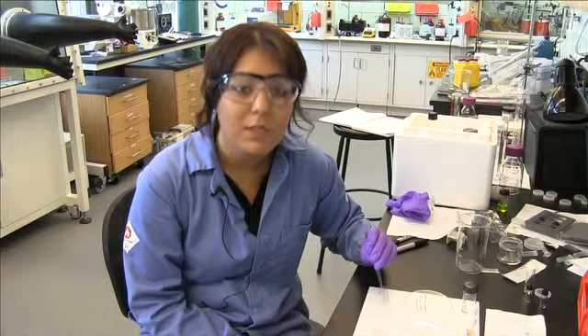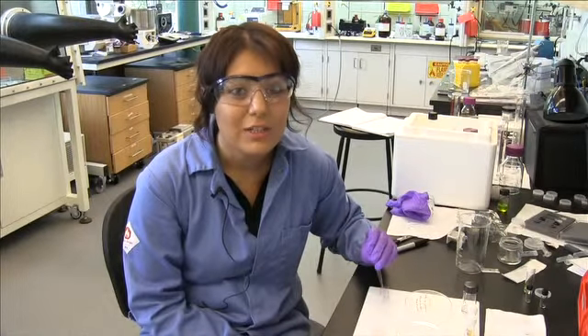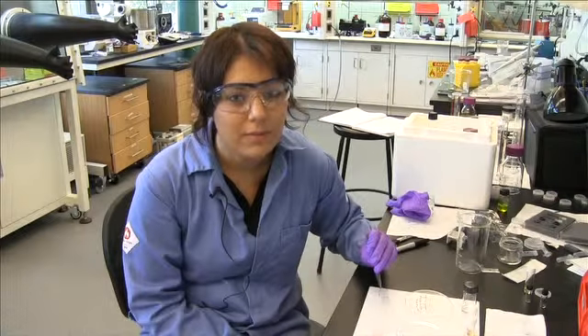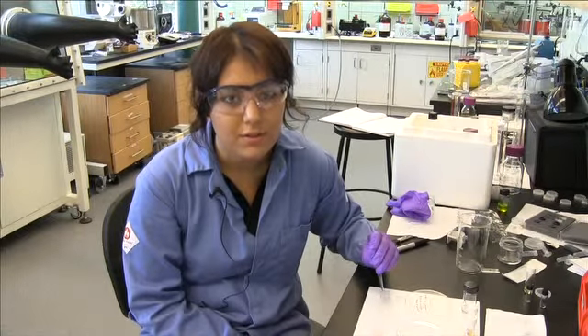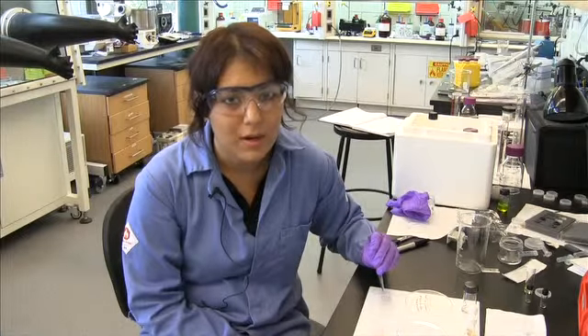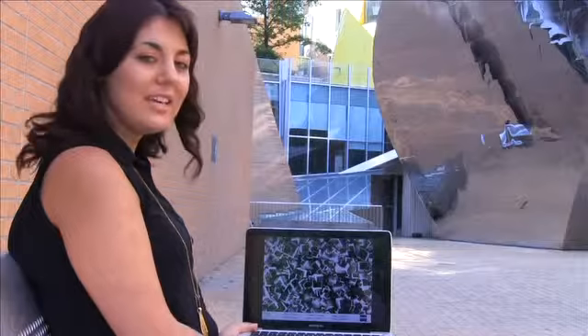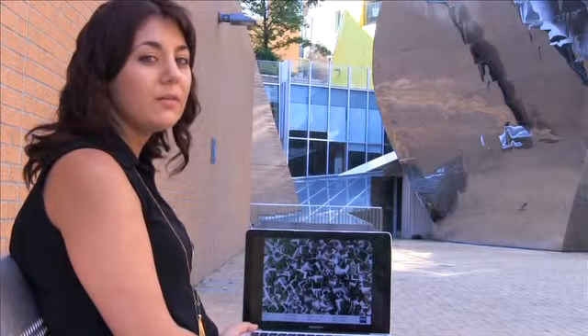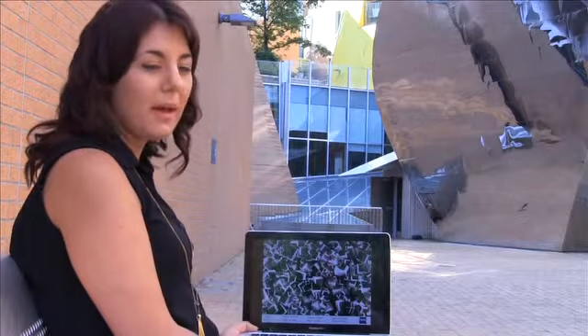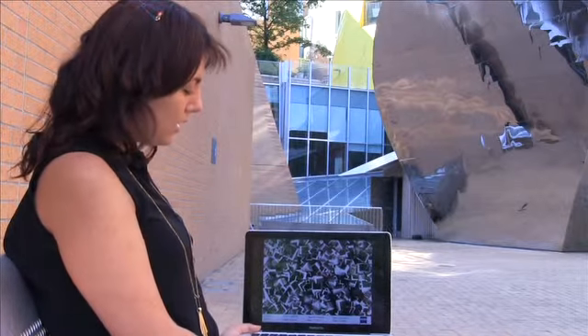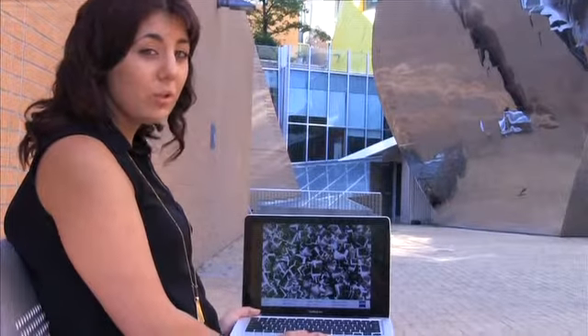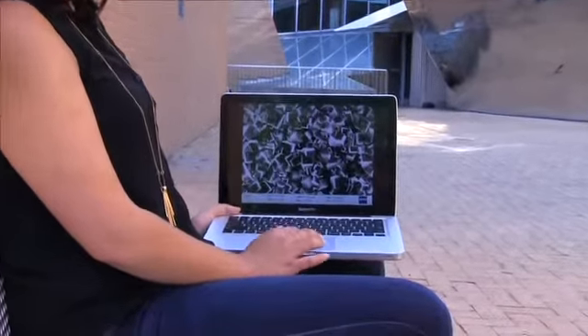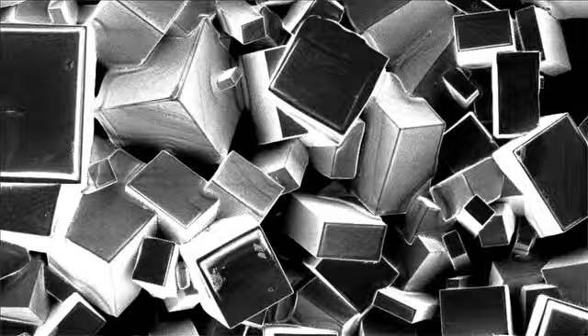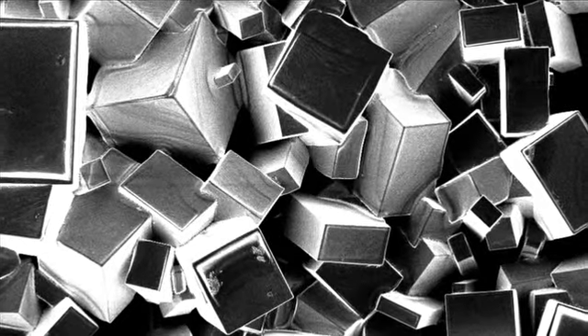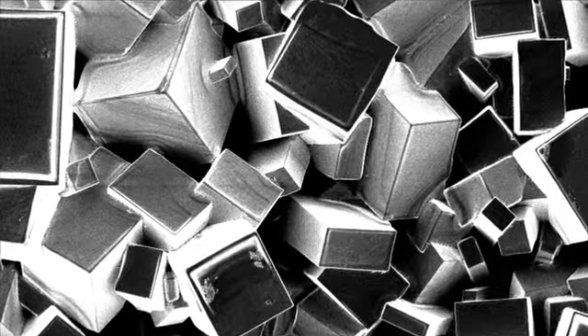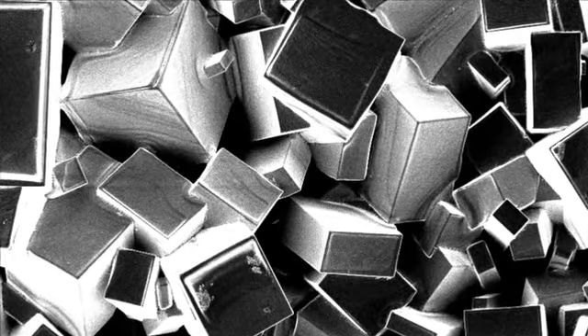Spin coating actually gives much more uniform coverage, and contrary to my initial belief, a spin-coated film made with exactly the same initial solution has very different optical and structural properties than the drop cast one. This is an SEM image that I took of one of the bulk films that I drop casted at room temperature, just pipetting outside on a cover slip. You can see that there are lots of well-defined cubic and tetragonal crystals. There are little cracks from annealing, and there are pretty big grain boundaries. Now these could act as traps for electrons and holes and excitons in a solar cell.